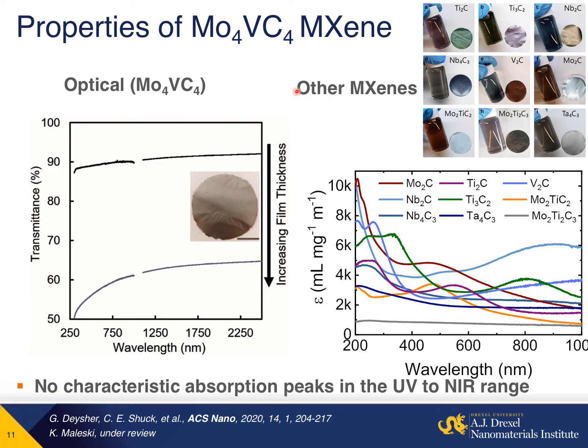With this MXene, initially I was a bit disappointed. We saw this dull gray color, which didn't seem too interesting. And when we looked at the optical properties, even up to 2500 nanometers, we saw really no characteristic absorption peaks. It seemed that this MXene really transmitted all light. This is in contrast to most other MXenes, which have characteristic absorptions between the UV and near IR regions, depending on the composition and structure.